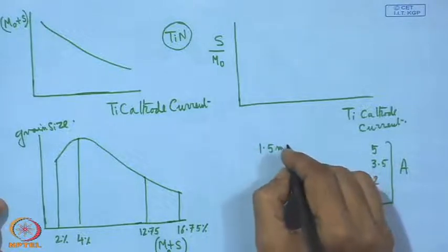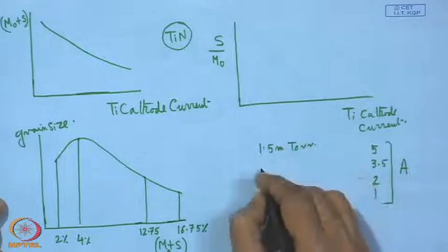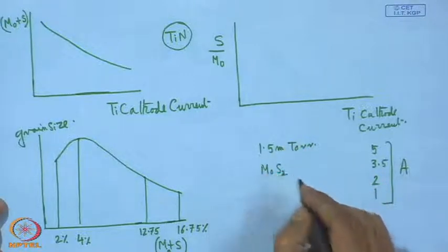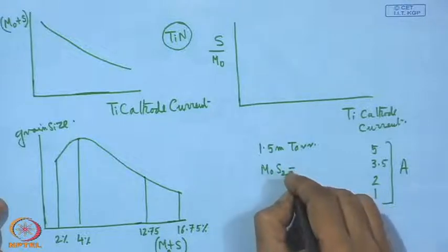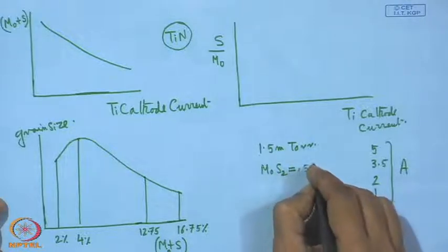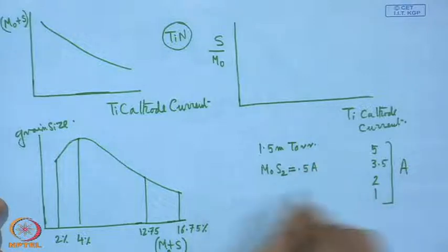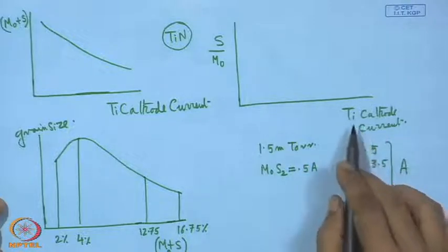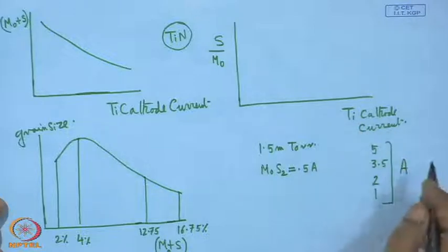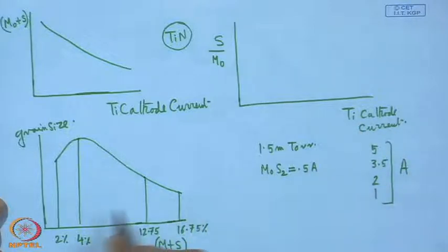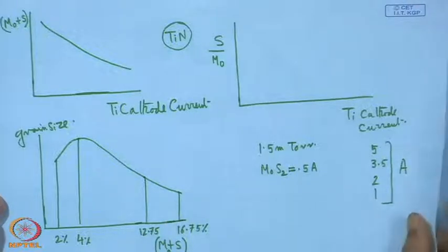This is a condition of deposition where the process pressure was 1.5 millitorr, the MoS2 cathode current was restricted to 0.5 ampere, and the cathode current of titanium was varied. With this, we can get a grain size of this order, and then comes a very important thing, that is the surface, that means the adhesion.